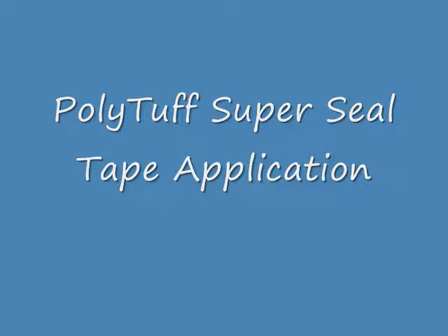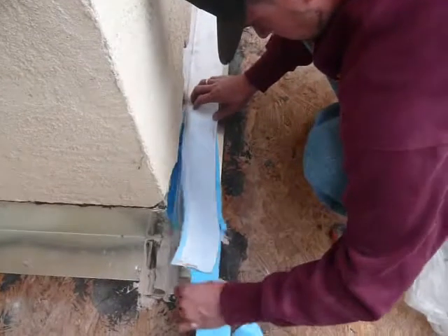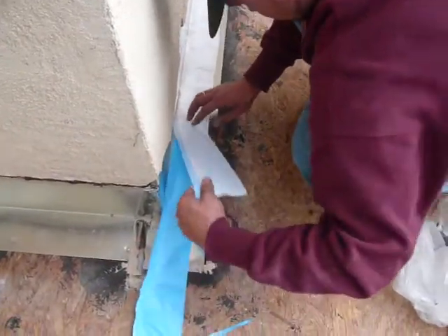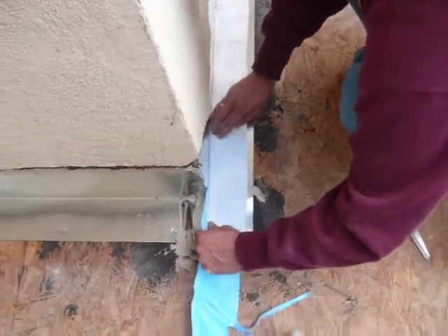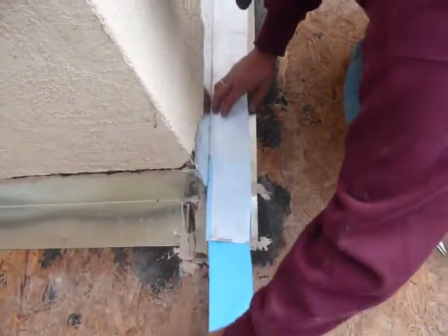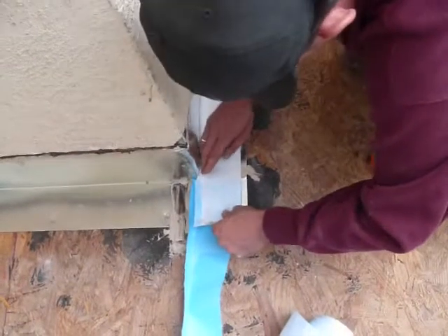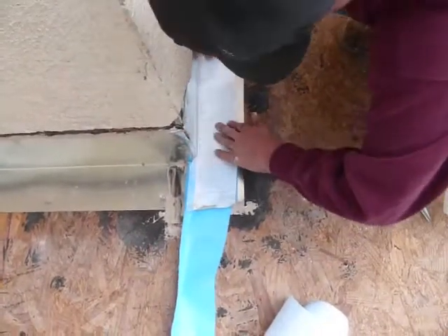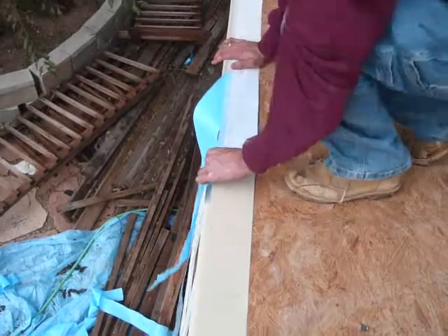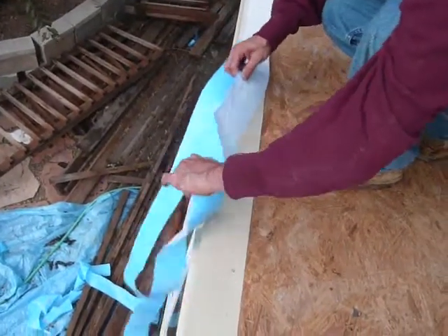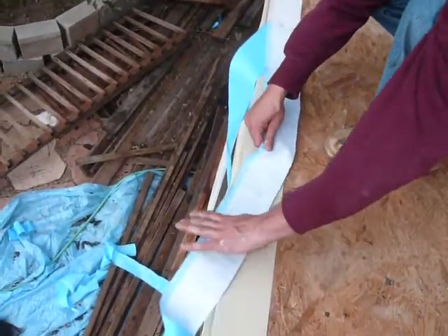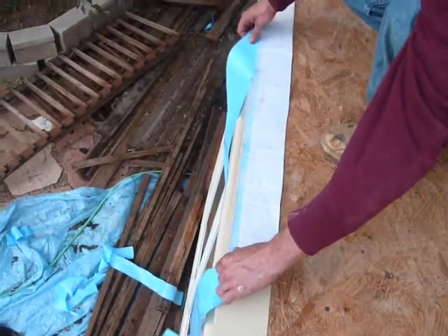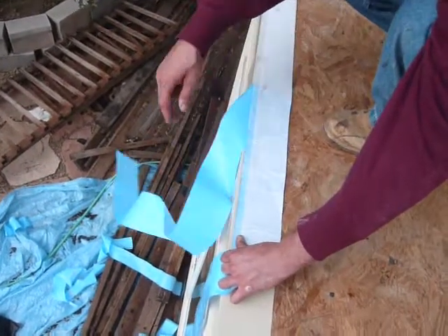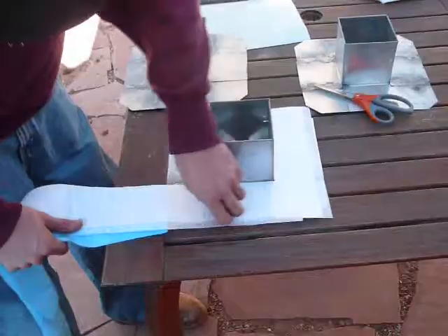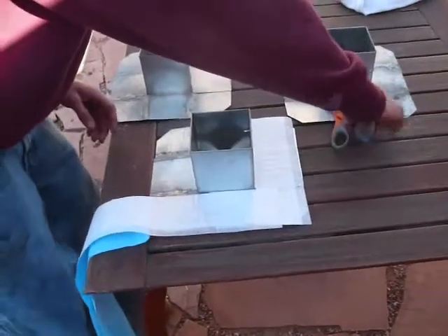The Super Seal tape is laid out along the horizontal leg and turned up about 1/16 of an inch onto the vertical leg of the metal flashing. It is tucked neatly into place to prevent any voids, and the plastic release film is pulled out from underneath the Super Seal tape. Hand pressure is sufficient to allow the adhesion of the tape to the metal flashing. Again, the tape is pulled out in advance, aligned along the metal flashing edge, and then the release film pulled out in front of it.